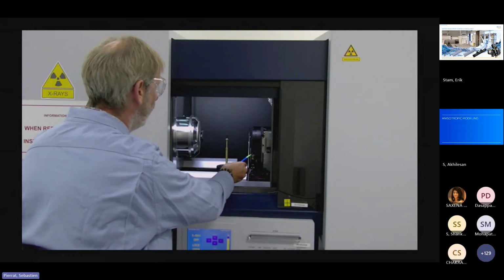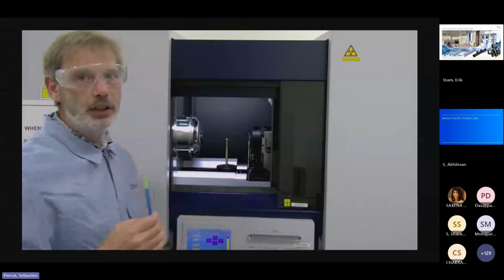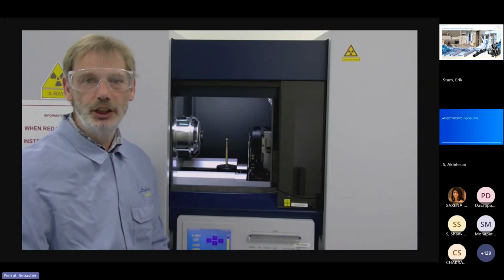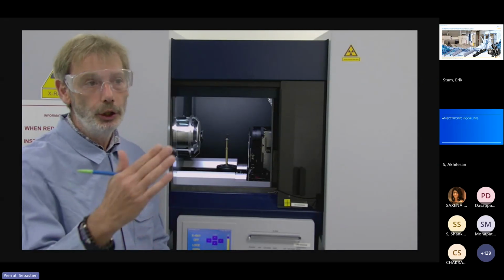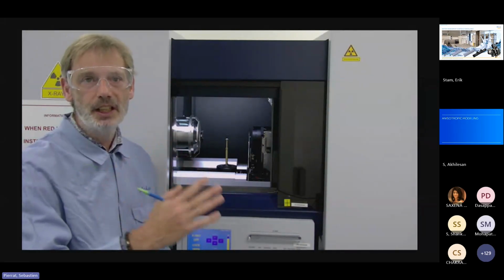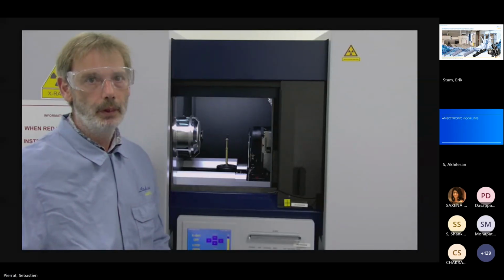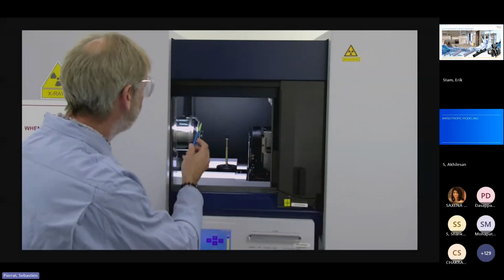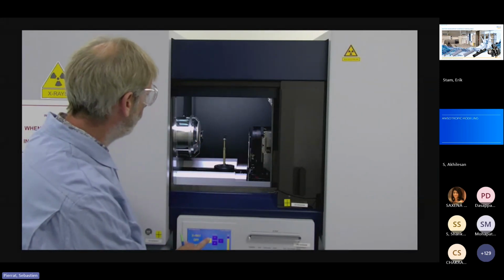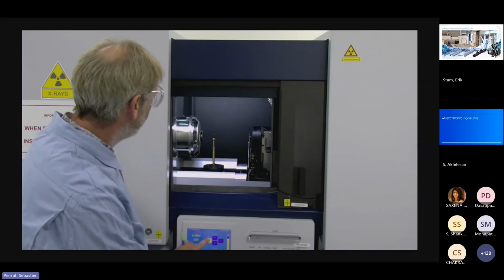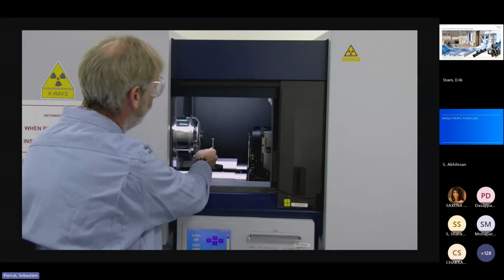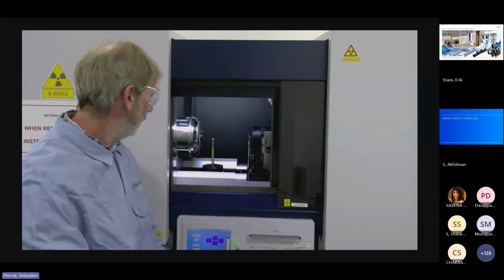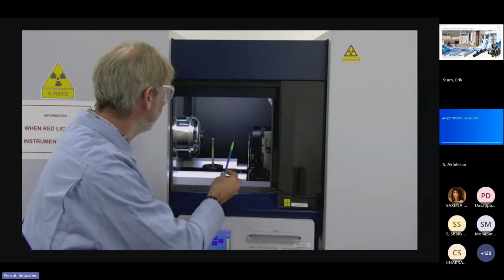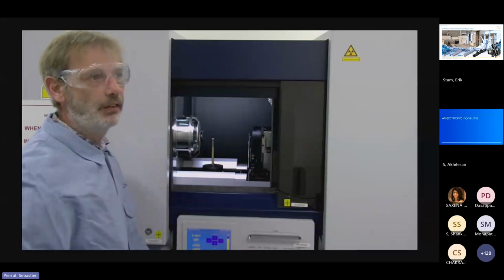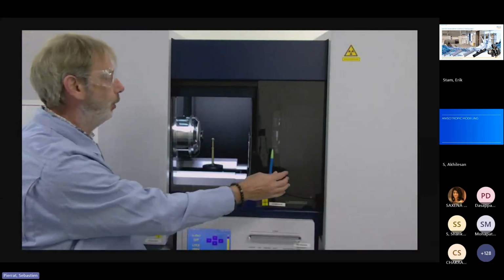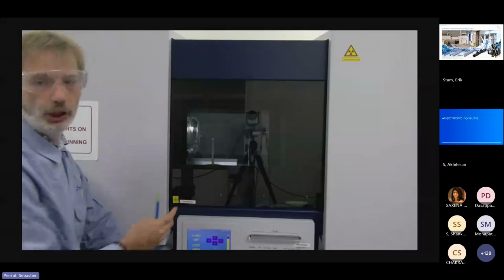Another component of the system is a filter wheel. This allows us to adjust the energy of the X-ray and optimize the contrast. We use different energy if we want to image glass fiber in a polymer or carbon fiber in a polymer. Another important parameter is the resolution. In the system we have, the resolution can be adjusted by changing the distance between the source and the sample, which brings some constraint on the sample size. For glass fiber, typically, I'm using a resolution of 3 micrometers, and this is typically the size of the sample that I'm using. I will now show you a bit more on the image acquisition itself.